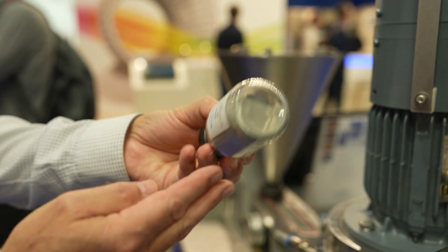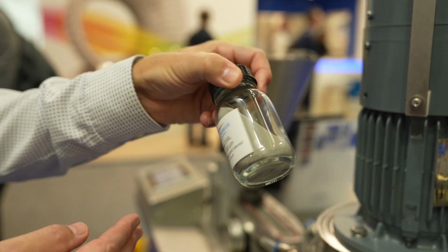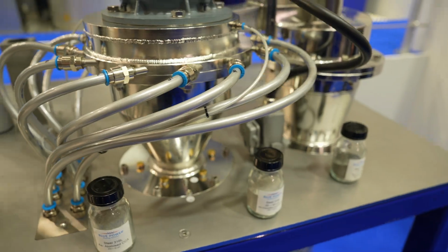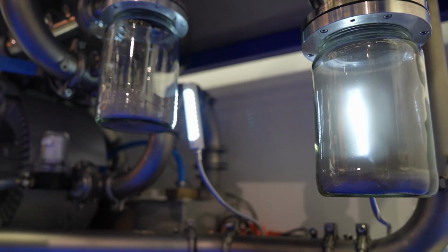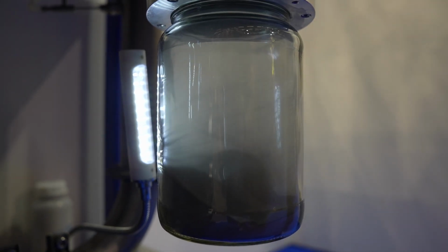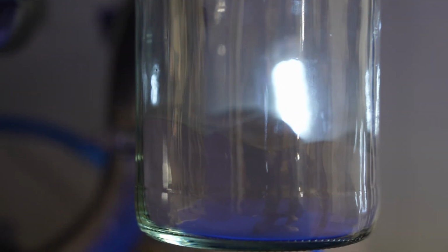So post-processing of the powder is very important to extract the usable size fraction and to make the powder flowable. So the system that we are offering for the post-processing step is a so-called air classifier that separates coarse from fine powder at different size regimes in a gas flow environment.